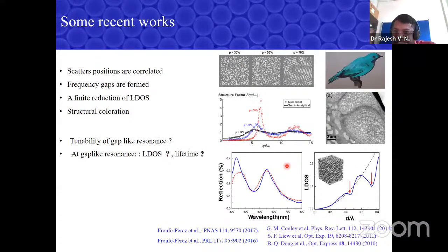That means there is a spatial correlation between the scatterers, so there is a short range order. It's not completely random, but there is a hidden short range order. There have been quite a lot of recent works. It actually follows from the C.V. Raman work, which is shown in my third slide. You can see that this is some literature, I think from a PNAS paper, where they're interested in how coloration comes because of short range order in these kinds of bird feathers.